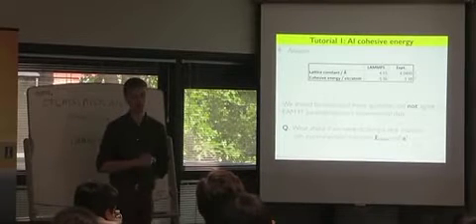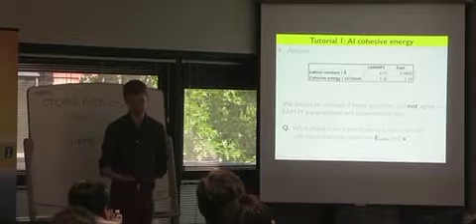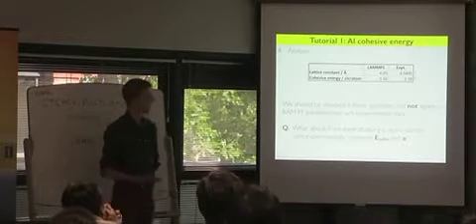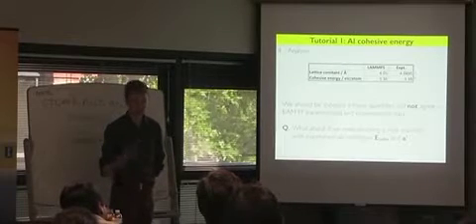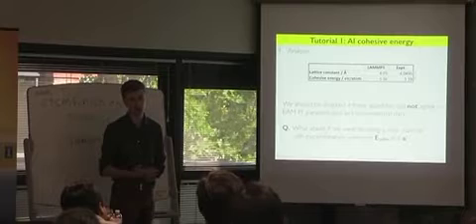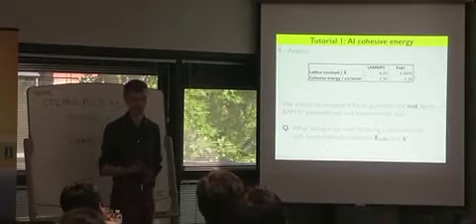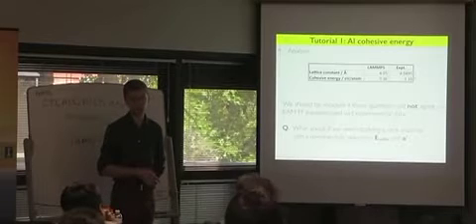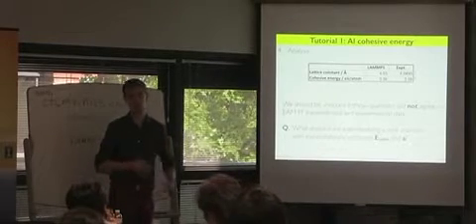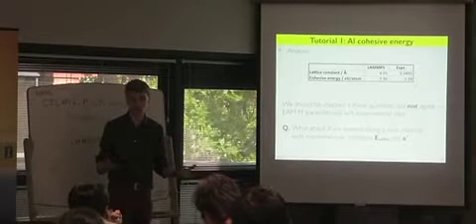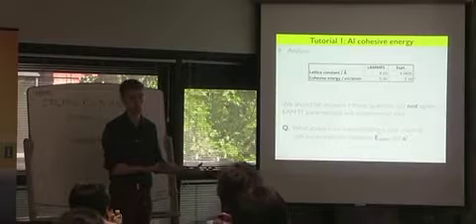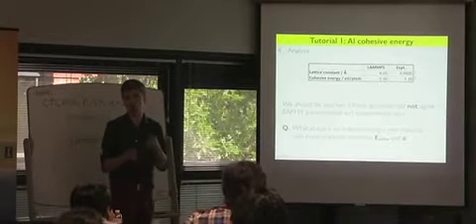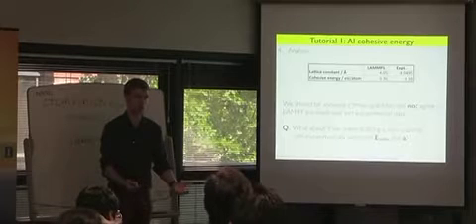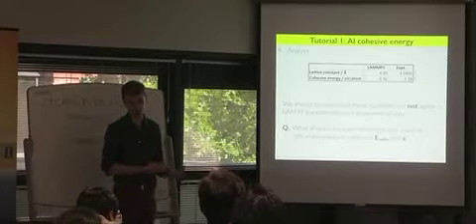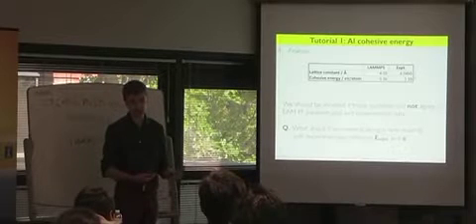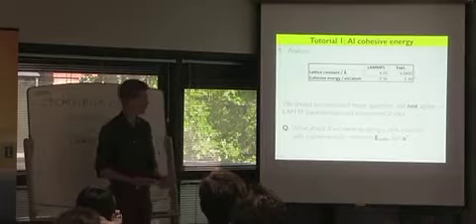But really, we should be shocked if these quantities did not agree. If they did not agree, it means our force field is terrible. And so the AL99 is a good force field, it does a nice job, and so it's good that those things agree. So of course this is a tutorial, it's a toy example, but one could think about if you discovered this brand new material, a high temperature semiconductor that is going to make you billions and billions of dollars, and you want to simulate it. Maybe you do some quantum mechanical calculations, you build a new force field, a brand new EAM potential that's never existed before, and you want to check that it's in line with the experiment. This might be one way of doing it, and if these things are off, that then gives you a route to start adjusting the parameters in your potential to reproduce reality. So it's sort of a toy example, but this is the way that potentials are fitted at the end of the day. So people who are designing EAM potentials are doing things like this and checking these things agree.